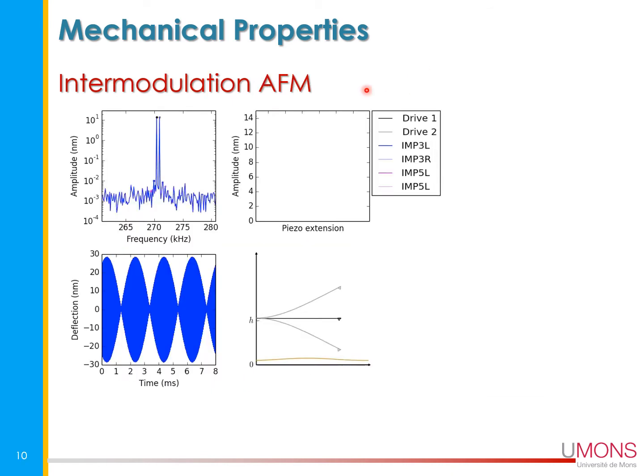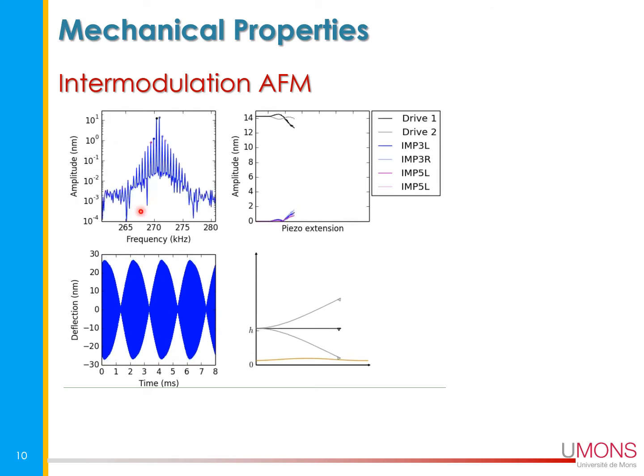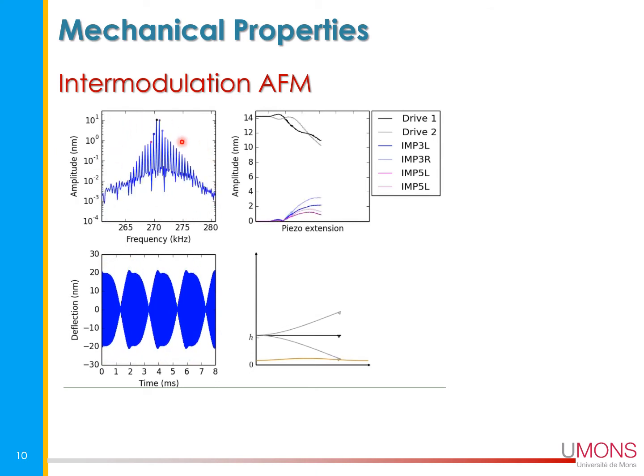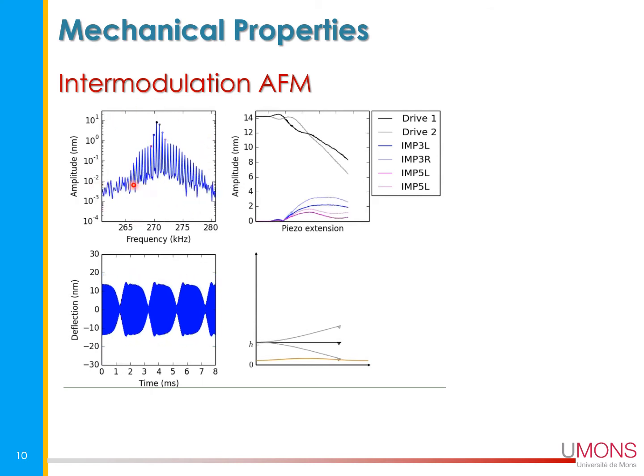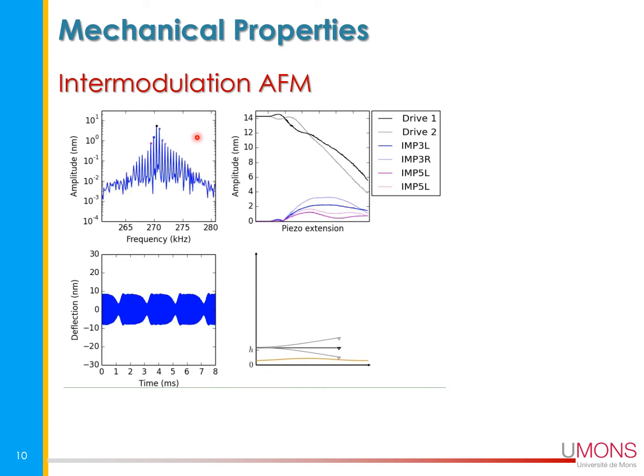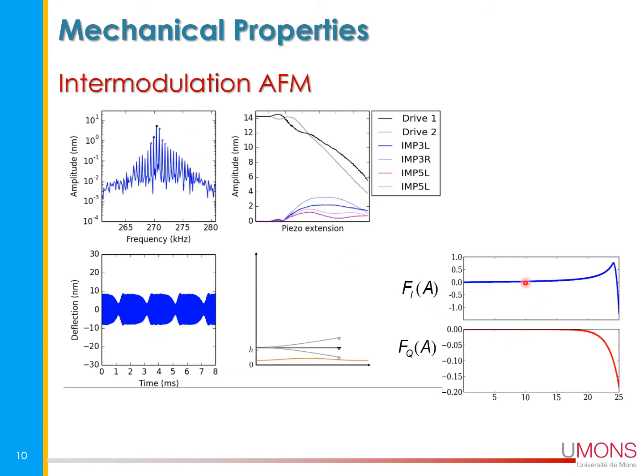Another mode which we will use also is the so-called intermodulation AFM. In this case, what you are sending to the cantilever to vibrate is 2 frequencies close to each other, and when the tip is interacting with the surface, you generate some side frequencies, some side bands corresponding to the intermodulation product. And when you have those spectra, actually, so the amplitude and the phase of all of these frequencies, it's possible to generate the evolution of the force in phase with the solicitation, or out of phase in quadrature with the solicitation. And these typical forces, you can analyze them to get, for instance, the viscoelastic properties.